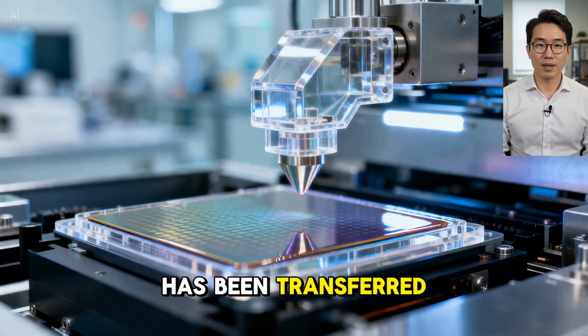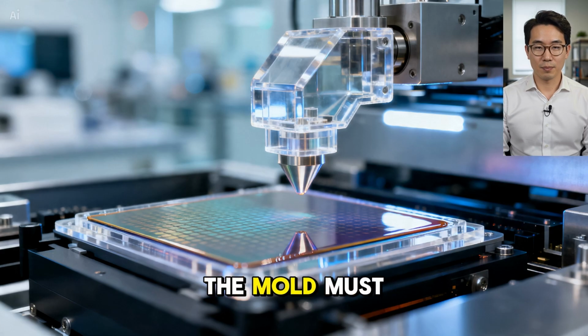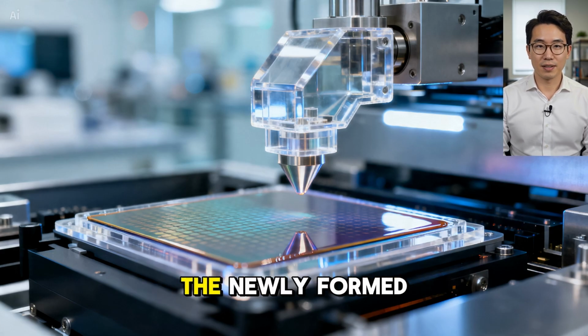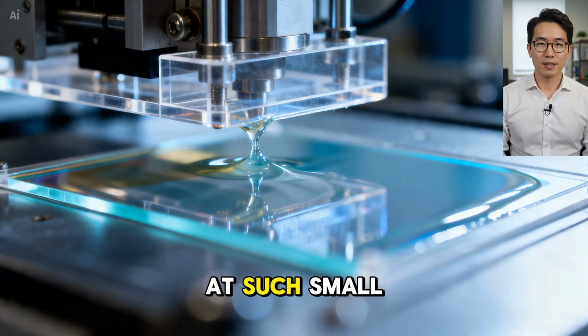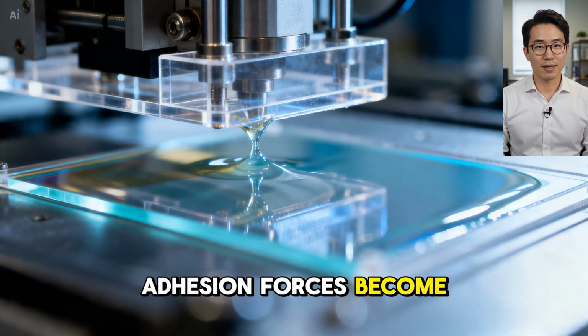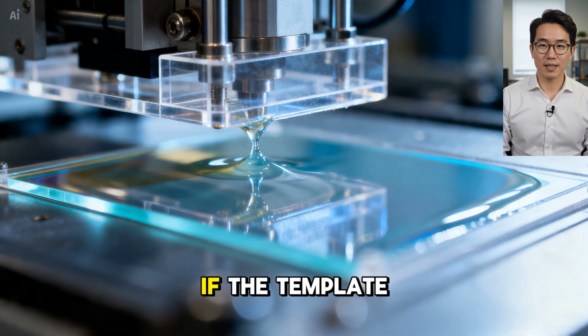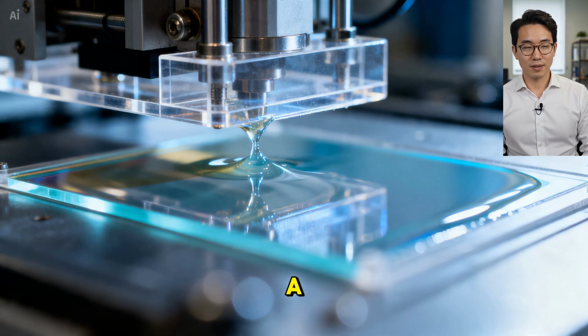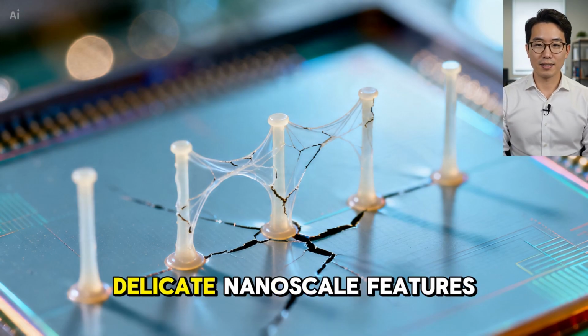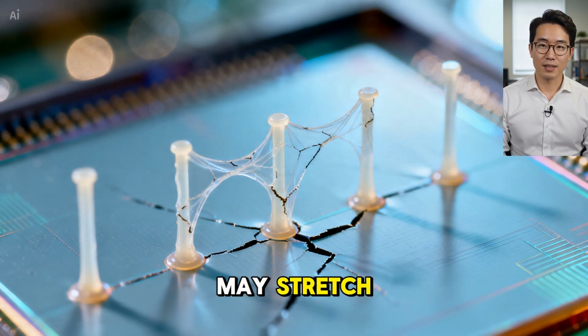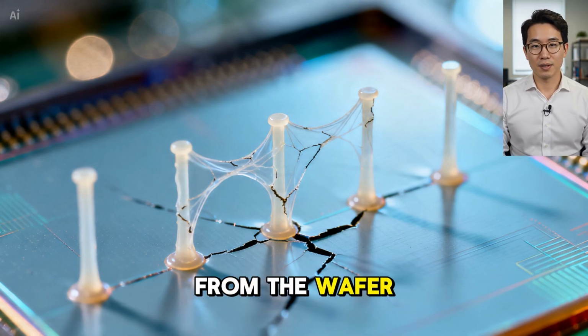Template separation introduces another layer of complexity. Once the pattern has been transferred and the resist is cured, the mold must detach cleanly without damaging the newly formed structures. At such small dimensions, adhesion forces become surprisingly significant. If the template sticks to the resist for even a fraction of a second too long, delicate nanoscale features may stretch, fracture, or lift away from the wafer entirely.